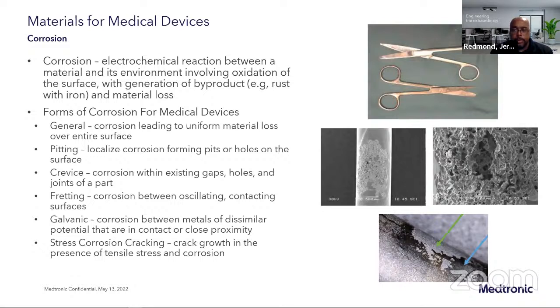And you can see some of those on the images on the screen where there's a pretty heavy localized corrosion attack where you've got quite a bit of pitting on the surface where you disrupt the metal. That can not only cause discoloration and a cosmetic issue, but it can also result in a potential for fracture of that material. Crevice corrosion is another one where you've got gaps or small holes on the surface of a part. Maybe they were designed into the part, or you have an assembly where you've got some overlapping surfaces with a small crevice, you can have corrosion in between those surfaces.